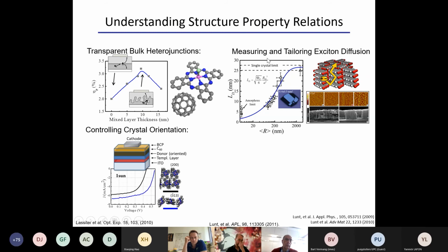So that's another area. Another aspect is that these materials have anisotropic crystal structures, and if we can orient their crystals in particular directions, we can take advantage of those anisotropic properties. If you get the right orientation, you can think about higher mobilities and higher exciton diffusion lengths, which is what we see here in the black and blue curves. We can increase the photocurrent, but it also affects the HOMO level by adjusting the crystal orientation. And so you can actually deepen the level and increase the voltage simultaneously. In this example where we had crystallites standing upright versus laying flat, we could just double the efficiency with the same material effectively.